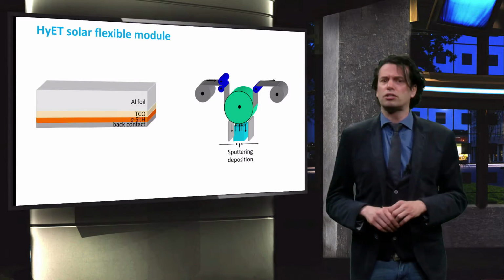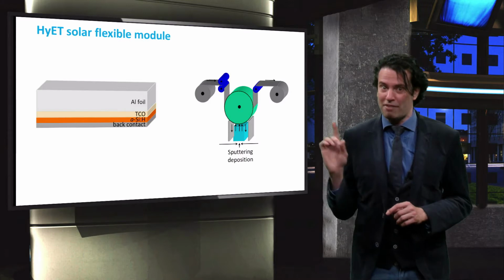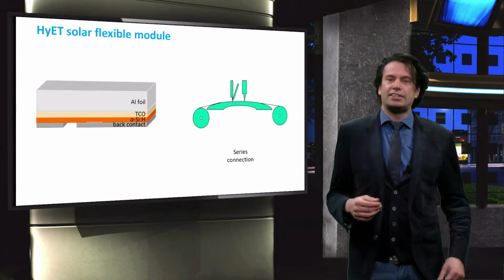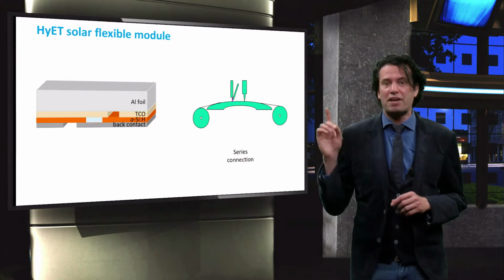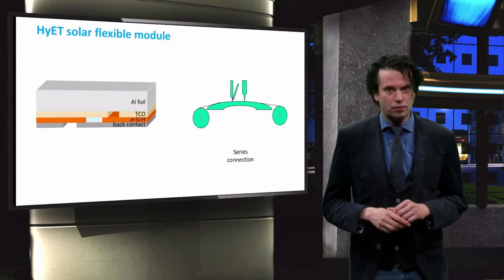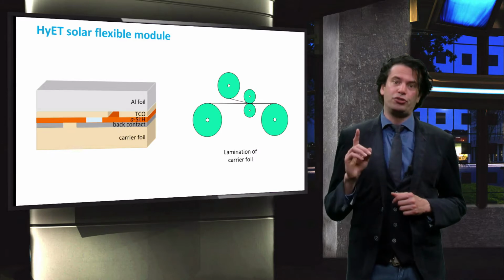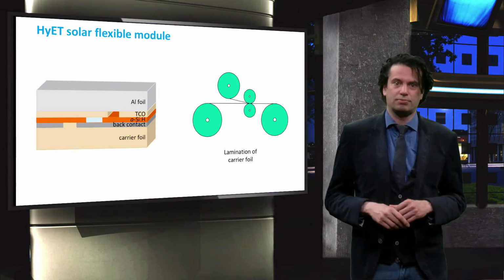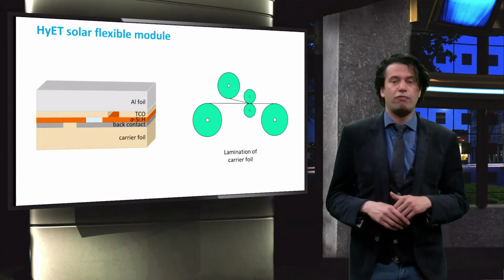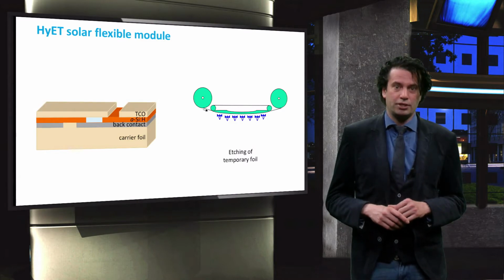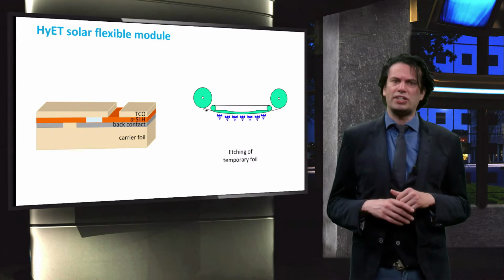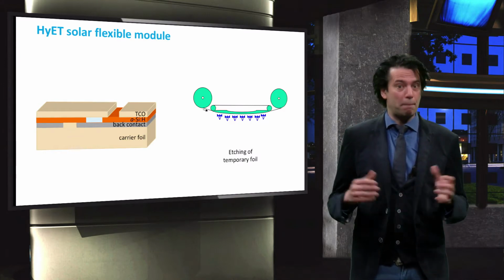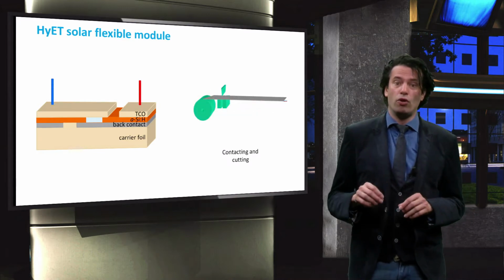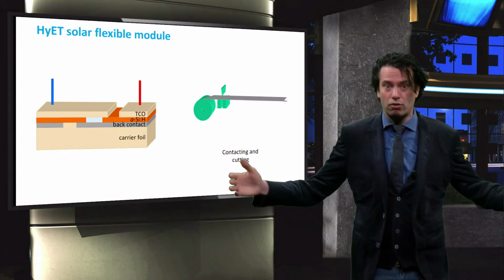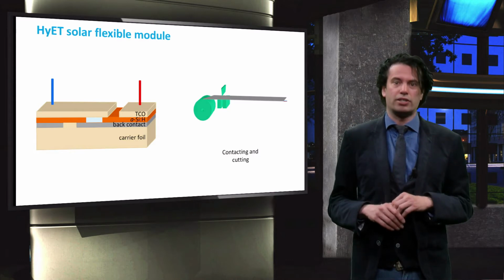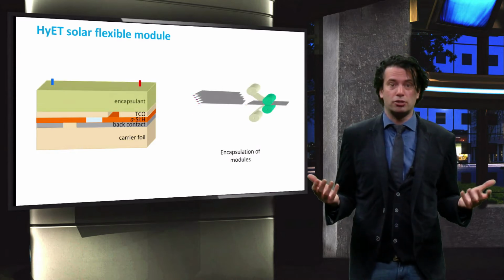For the sharp observers among us, indeed, no separate laser scribing step has yet been performed. The monolithic series integration of the module is realized during a unique single patterning step by means of laser scribing and printing. Following the series integration, a conducting carrier foil is deposited on top of the back contact. After lamination of this permanent carrier foil, the aluminium foil is etched away. The aluminium is just a temporary carrier that is required to withstand the temperatures of the atmospheric pressure CVD and PE-CVD process. Then the foil on the roll, which can in principle be up to kilometers long, is cut to the required size and contact wires are added. During the final step of the process, the module is encapsulated.